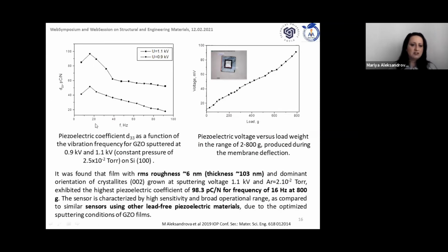Actually, it is a low frequency element that we succeeded to produce at the highest possible sputtering voltage of the plasma, 1.1 kilovolts. The roughness of the film is nearly 6 nanometers for a total thickness of almost 100 nanometers. It is a low frequency element suitable for sensing applications. It exhibits good linearity, with a deviation from linearity of less than 2%, and reacts in the range from a few to 800 grams.